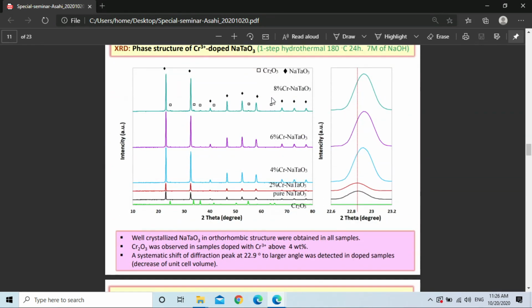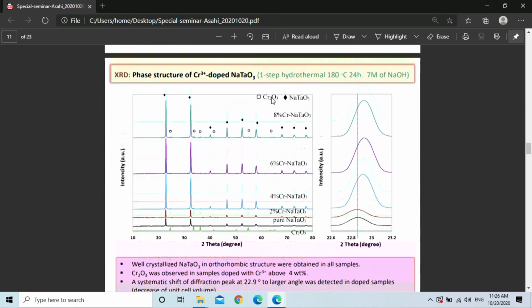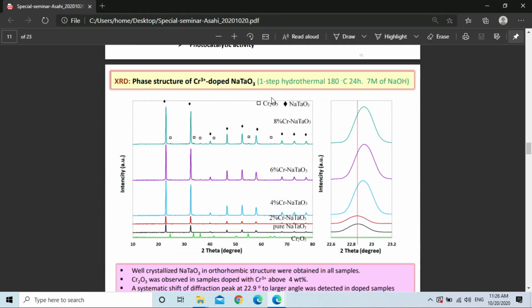This is the XRD of doped and undoped sodium tantalate. We can see that all are well crystallized sodium tantalate in orthorhombic structure, and quite pure, without any other phase. But at more than 4% of chromium doping, we can observe a small amount of chromium oxide peak. It means the excess amount of chromium doping precipitates as chromium oxide.